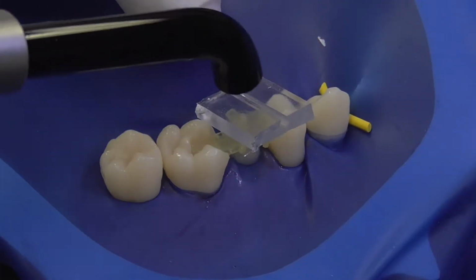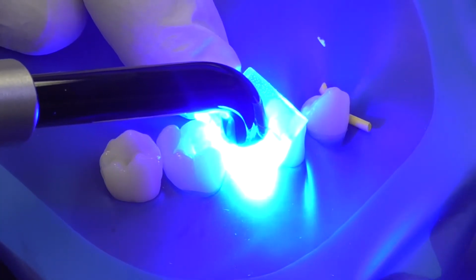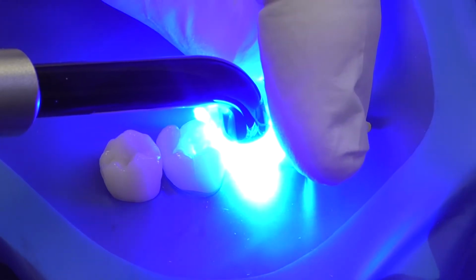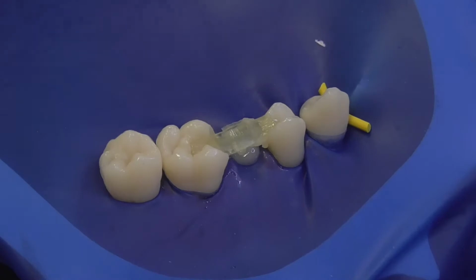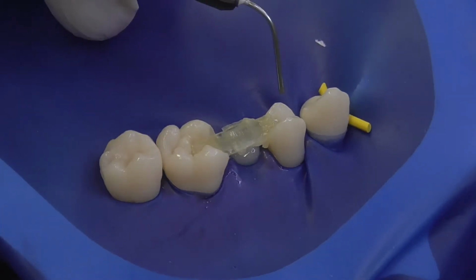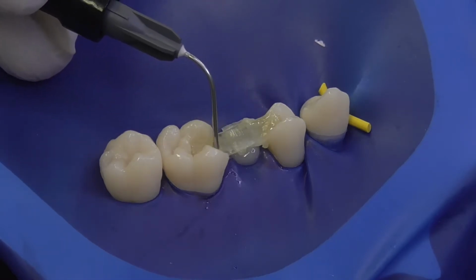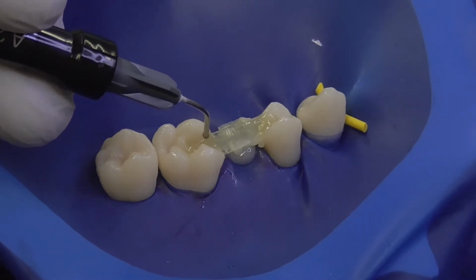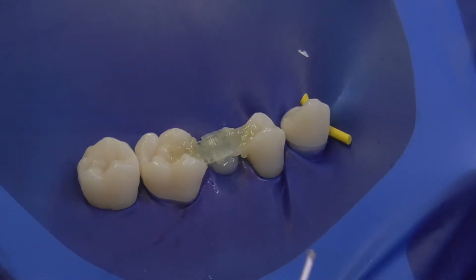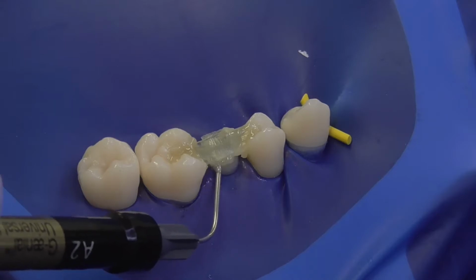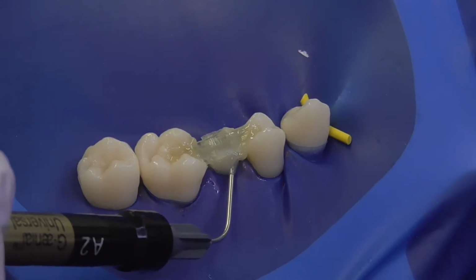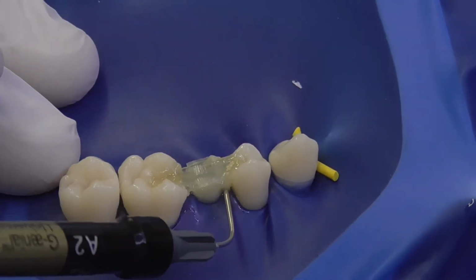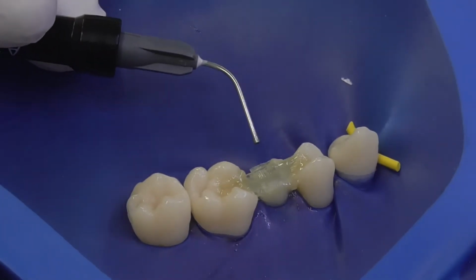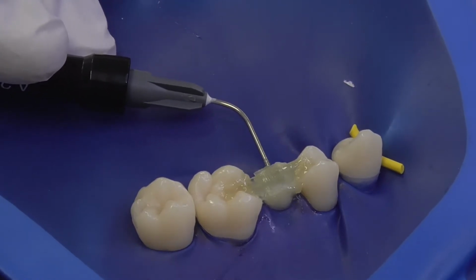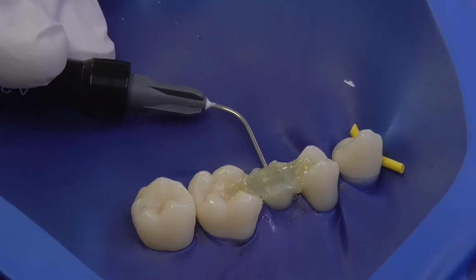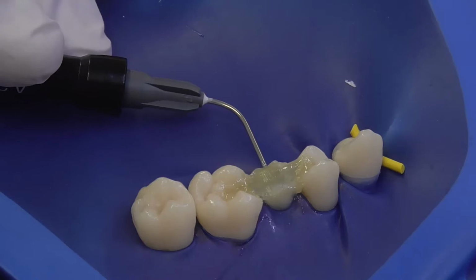And then please note that in all of these placement of the fibers, we are putting everX flow between the fiber layers, because that with the microfibers is guaranteeing the bonding of these layers strongly together. Now we have almost ready framework. Next step is that we seal all possible even microscopic gaps, which can be seen with the flowable resin, in this case injectable composite resin material from GC. And then gradually the framework with the sealing starts to look like a framework of whatever bridge work. In this case is the framework made out of non-metallic toughened fibre-reinforced composite material.